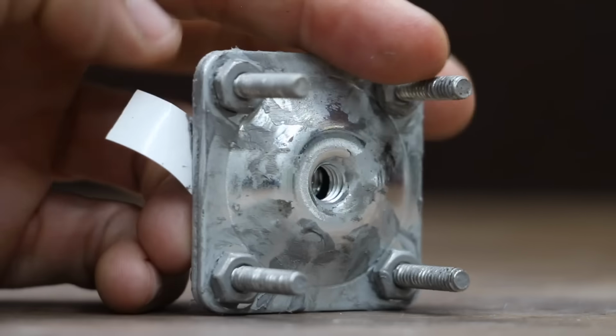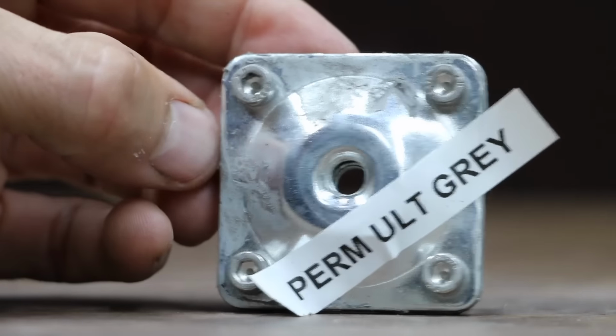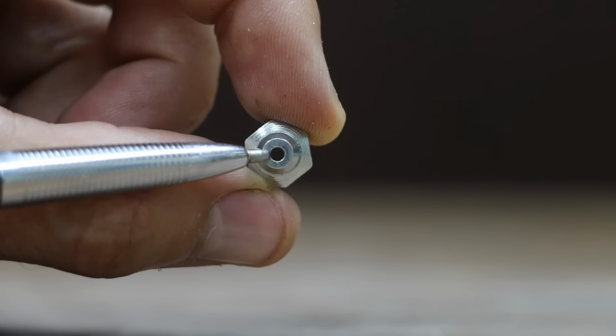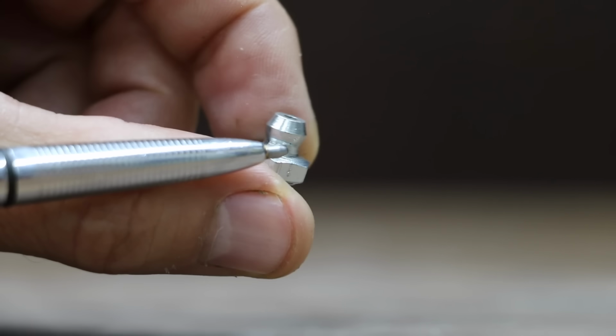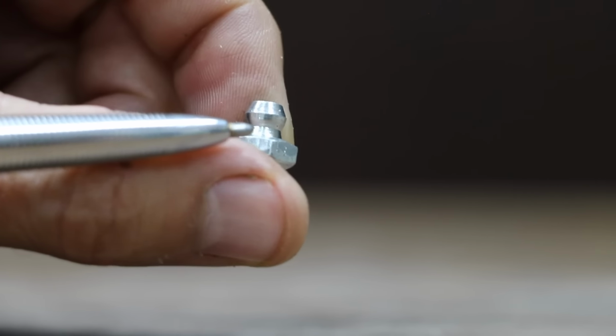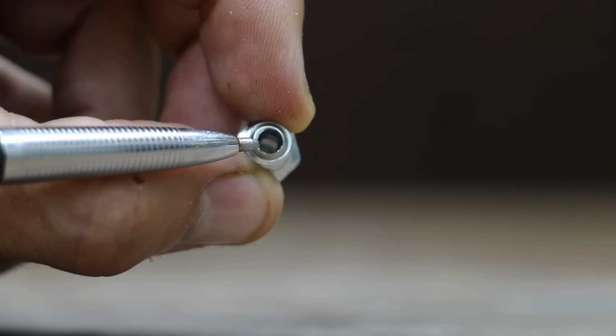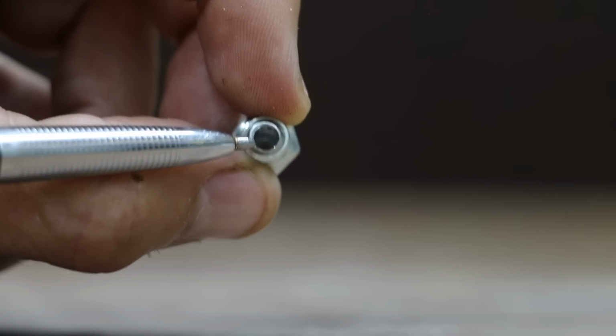All of the clamshell test pieces have had 72 hours to cure with the center open to help the curing process. I went ahead and removed the ball and spring from the grease fitting to keep that from interfering with the test results. I'll be pressurizing the test pieces with jack oil, which has about the same viscosity as motor oil that's used in the car engine.